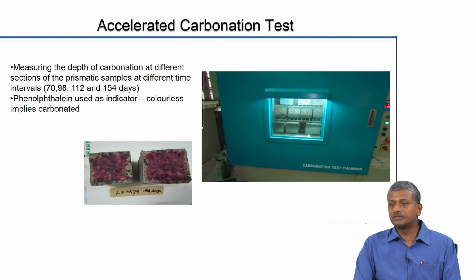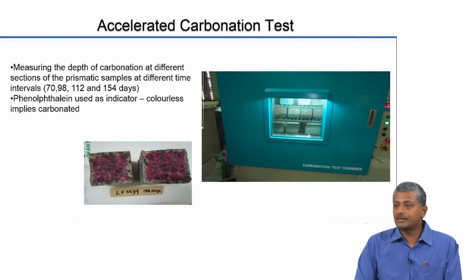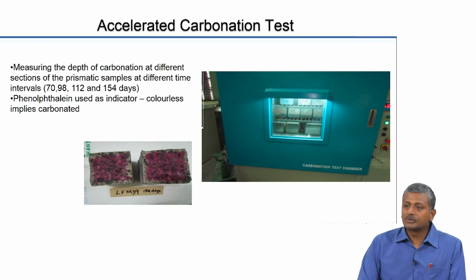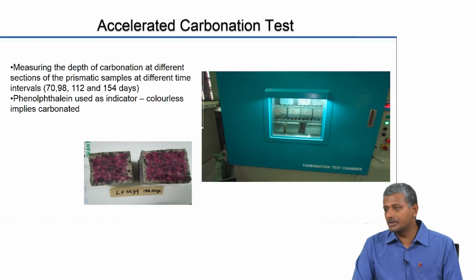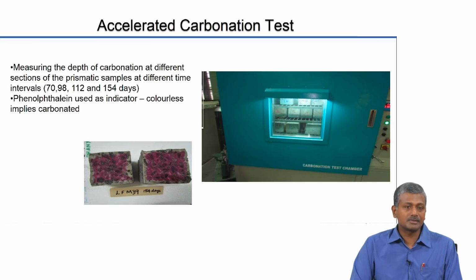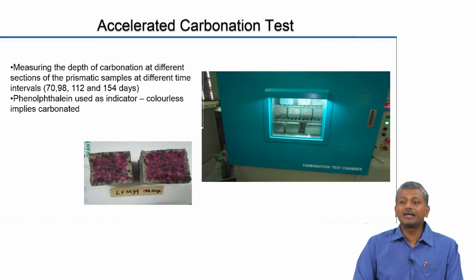Now, the other diffusion test is the carbonation test. So, here you subject your concrete to accelerated carbon dioxide environments, because what is the carbon dioxide content of the atmosphere? 0.03 or 0.04, yeah, 0.04% is the extent of CO2 in the atmosphere. So, if you leave your specimens out for natural carbonation, it will take a long time for you to get the result, which indicates the potential for the material to resist CO2 propagation into the concrete.